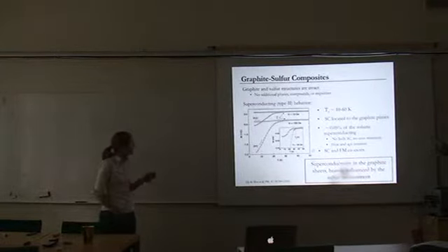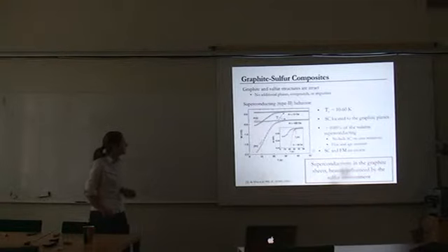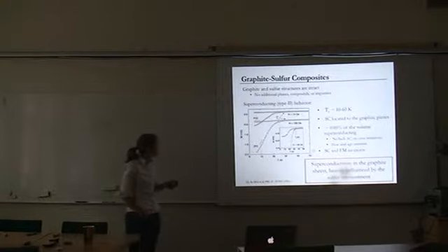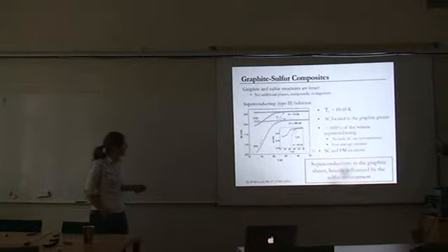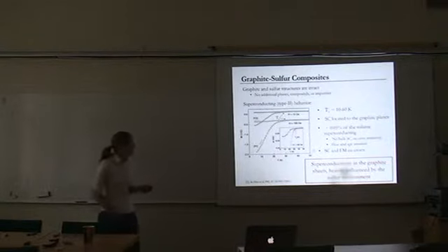And the superconducting behavior is very typical for type 2. You have the magnetization versus temperature. You heat in zero field, you get this curve, and then you cool in field, and you don't retrace, and TC is where these two curves start to depart from each other. So here TC is around 30 Kelvin. The same group, or actually several groups, had measured TC up to about 60 Kelvin. Most are maybe around 30.